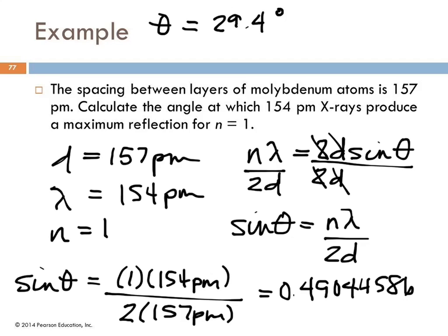So using this particular X-ray on molybdenum, when you get to an angle of 29.4 degrees, you're going to expect to see constructive interference on the pattern that comes out. And as you move past that, it will become less constructive and more destructive. And you can go through angles, and it'll be constructive, gradually to destructive, back to constructive as you change the angle. Any questions?